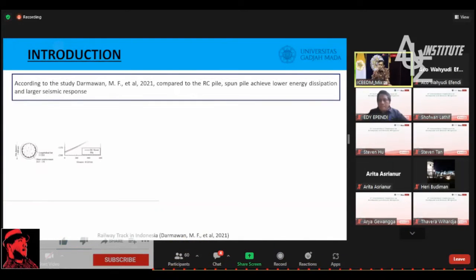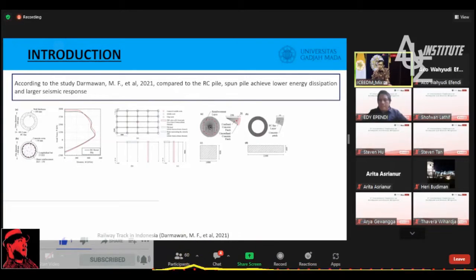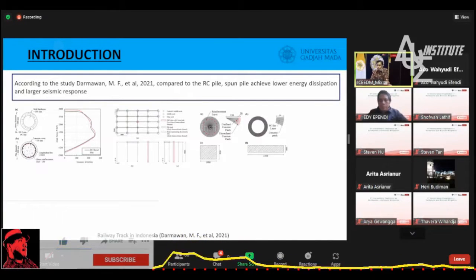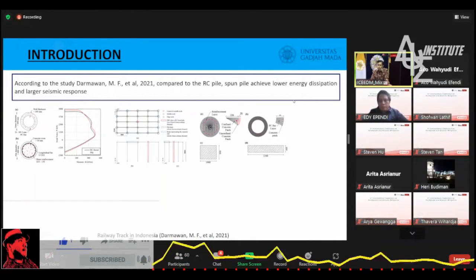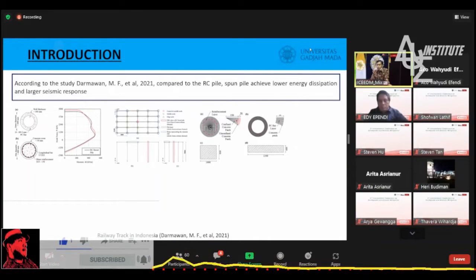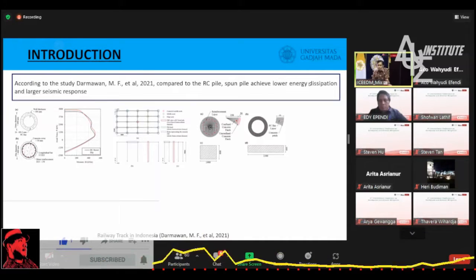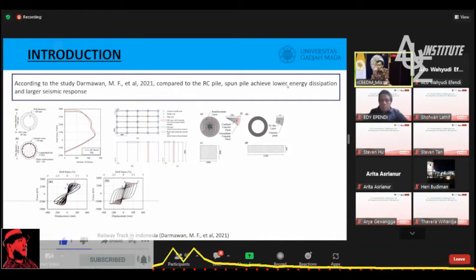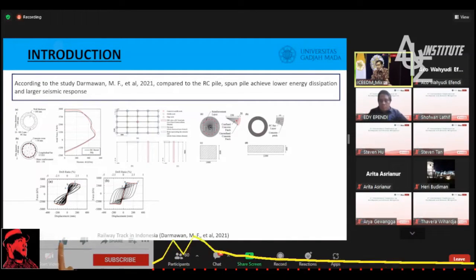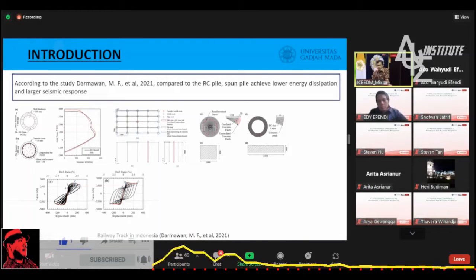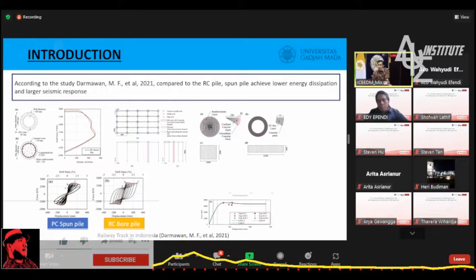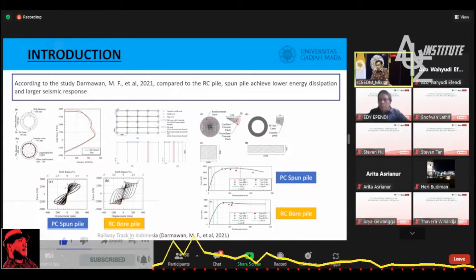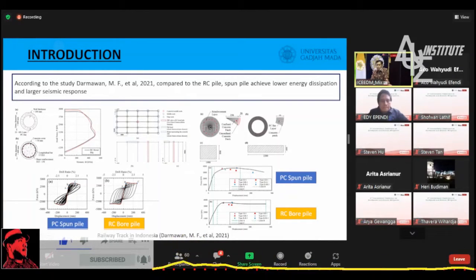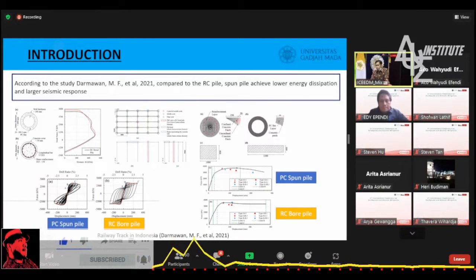Also, in some previous study, there is a comparison between the slab-on-pile with spun pile and RC pile. According to the result, at the left is the hysteresis loop of the slab-on-pile with spun pile, and at the right, B, is the slab-on-pile with RC pile. Based on the pushover analysis and comparing the maximum response under nonlinear time history analysis, the RC pile has less response, which means it has better performance compared to the spun pile.